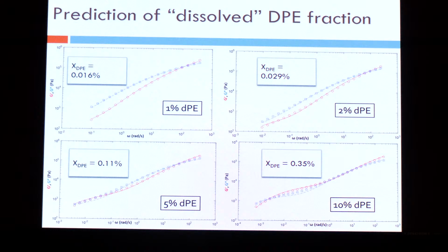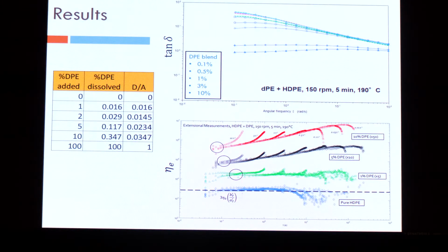These measurements are done at the same temperature, but there are qualitatively different graphs that you will see. So even a tiny amount of that disentangled polymer that dissolves in the high density polyethylene, the rheological behavior significantly changes. Right, and so this table at the left summarizes the entire data. The first column is how much DPE I have added. The middle column is how much is dissolved. And the third column is the ratio between dissolved and added. And you'll see that really a tiny amount of what I have added actually dissolves. But that tiny amount has qualitatively changed the flow behavior of the polyethylene.